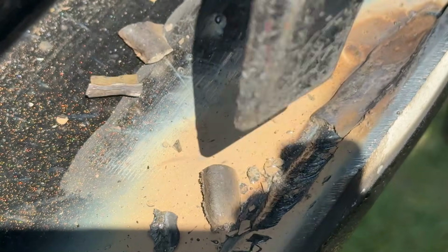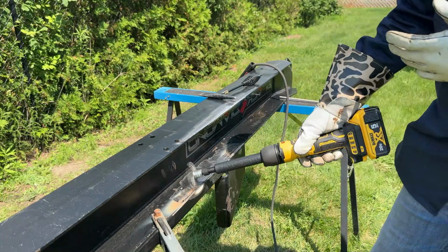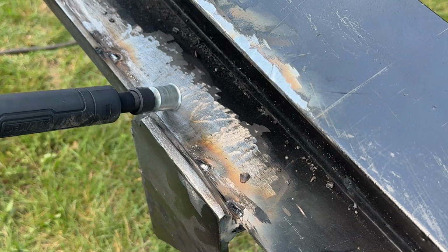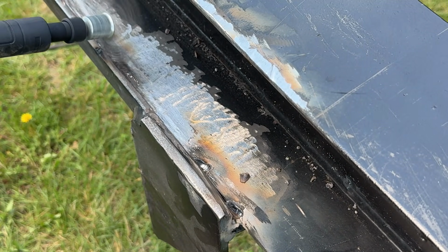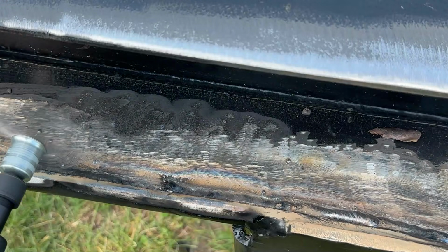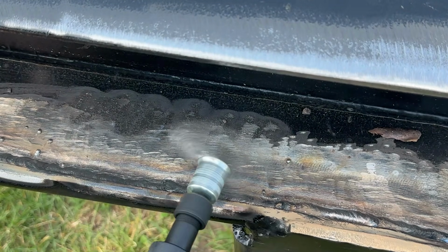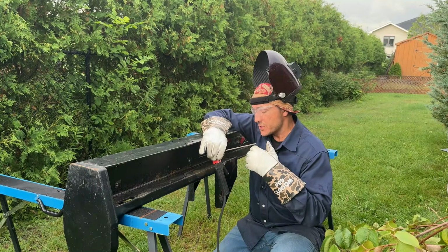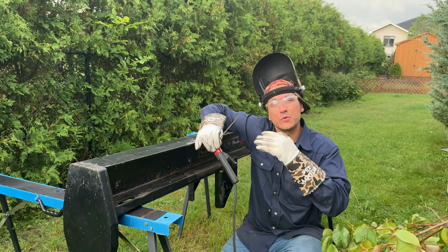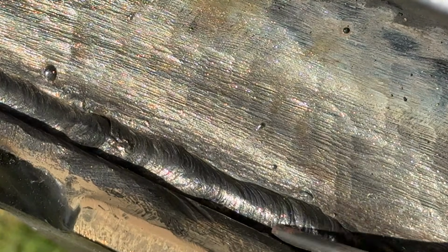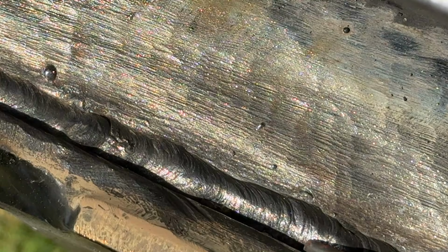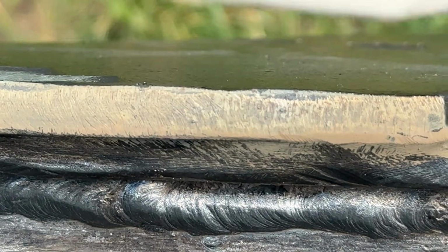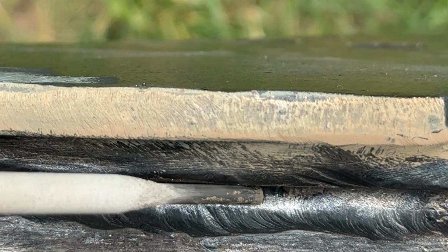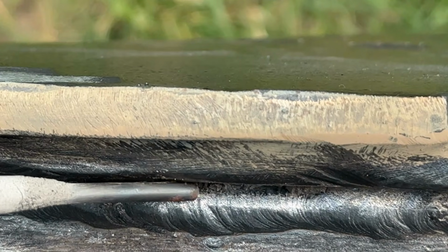As always, cleaning in between welds, chipping, then using some form of wire wheel to get it nice and shiny. This works well at making sure we get rid of all that slag. Here's a great example of how slag got trapped in my weld and I didn't even know about it. So I had a weld that wasn't completely fused or washed up into the wall of this plate right here, and it caused kind of this overlap, as you can see. So much that you've got a bit of a groove, and I can fit my rod right in there.